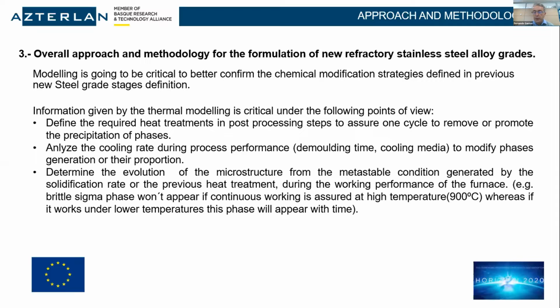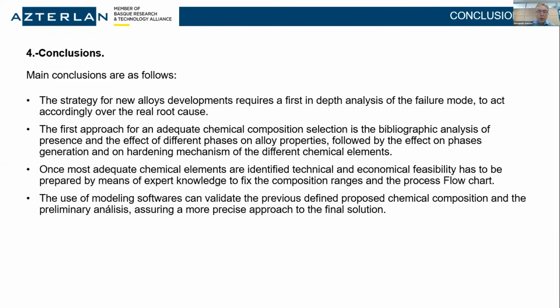time. Okay, so conclusions. We are now ongoing with the development of new alloys. The evolution of these alloys, we have preliminary data of tests of creep. It's quite promising, the selection of chemical composition and additions that we have made. We are obtaining at this time improvements of around 10 to 20% in creep. We have to fix that and consolidate it, but of course, preliminary data are quite promising.